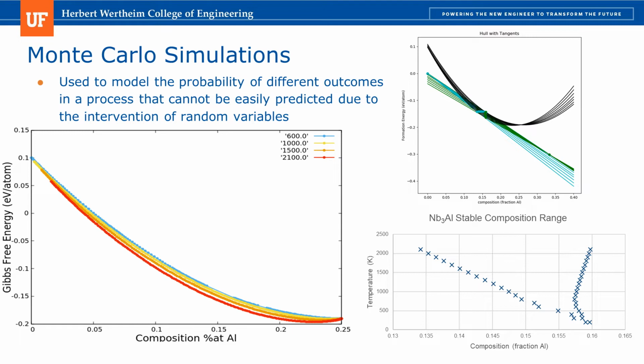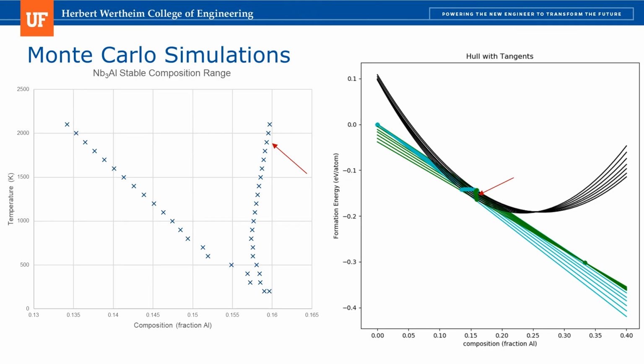The Gibbs free energy curves of the A15 phases were compared to the two stable competing phases. Each cross represents the x intersection point of the tangent line to the energy curve of the A15 phase that passes through the point that represents the energy of the competing phase. This describes our region of phase stability.